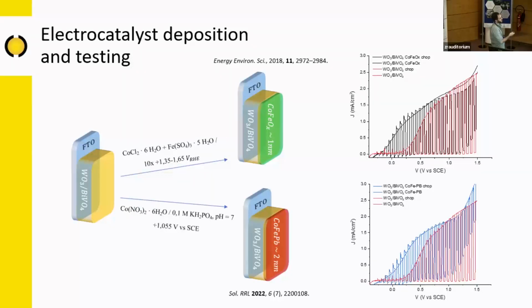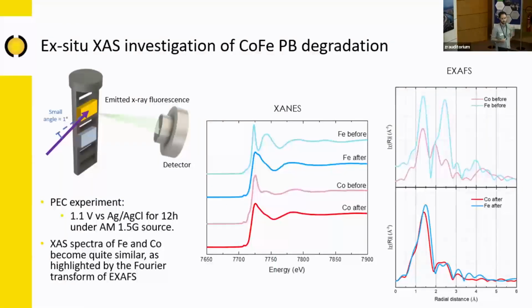One thing I want you to notice is that we have a very thin layer of the catalyst on the surface of these photoanodes. So if we want to investigate these properties, we have to deal with a very diluted sample. And we're also dealing with a sample that is very thin. So we have to work in X-ray absorption spectroscopy. It doesn't make much sense to work in diffraction, for instance. And we also have to work in fluorescence, as we basically have a very thin sample.